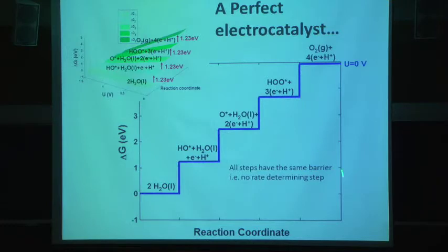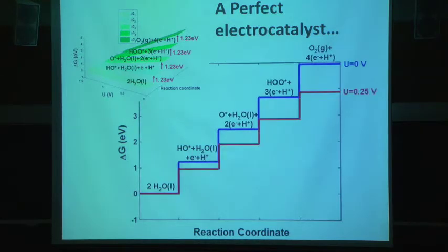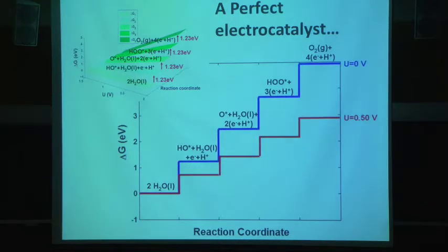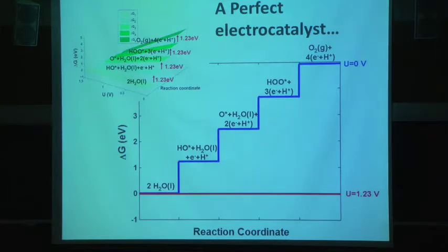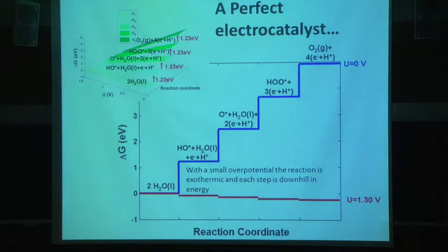So here at open circuit, it's uphill. We know water doesn't spontaneously decompose. We have to put energy in. And as we start applying a potential, let's say we apply 1/4 volt, then each step comes down by a proportional amount. If we go even more, right, you can see that as we get to 1.23 volts, at that potential, the reaction is now thermoneutral. And if I go just a little bit more, every step is exothermic and downhill. What that implies is that since every step is exothermic, it would be spontaneous. And since they're all downhill, the barriers are presumably going to be small, and the reaction would proceed rapidly. That is what would be a perfect catalyst in this case.